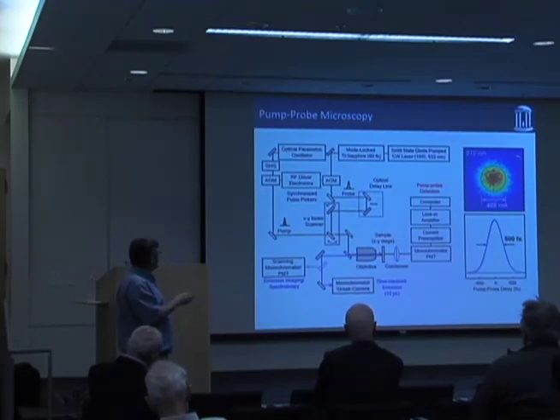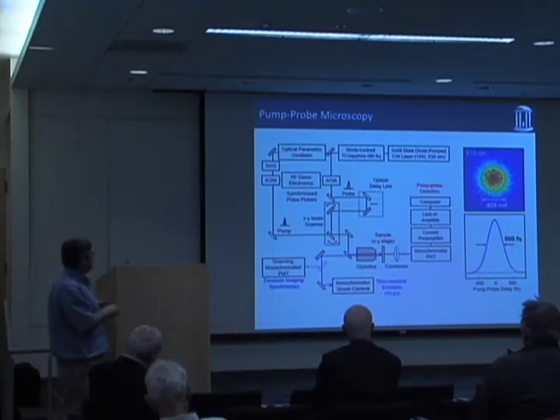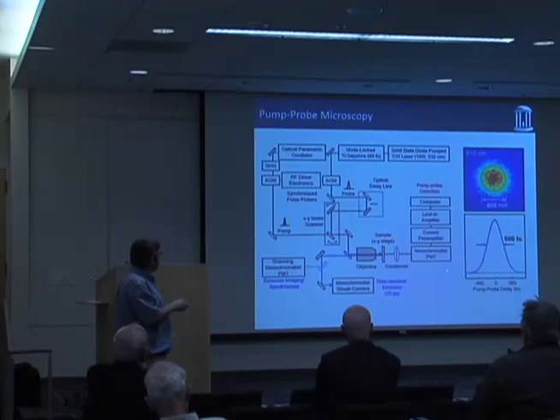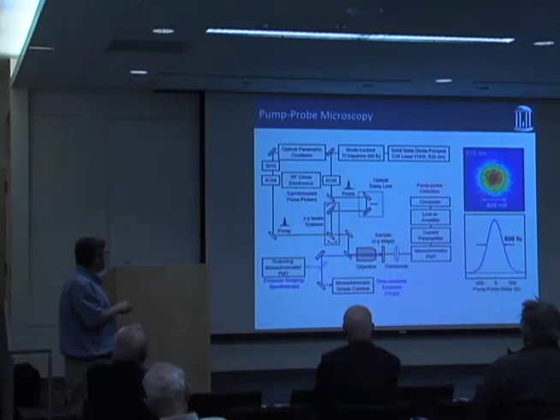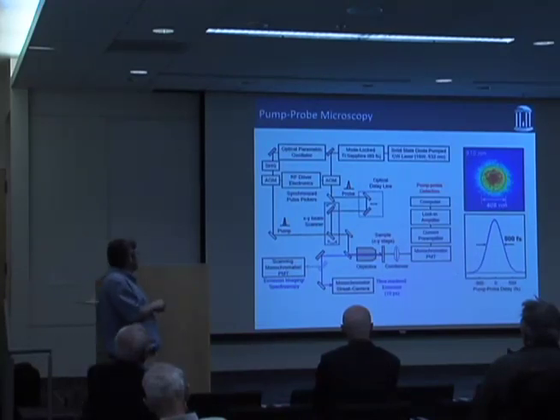This is an example of our spatial resolution. With 800 nanometer light, we can get somewhere down around 400 nanometer spatial resolution in a 2-photon excitation mode. If I did this with single photon with 400, that's about where we'd be as well. This is the time resolution of the instrument. This was measured at the sample, so we get about 500 femtosecond temporal resolution.